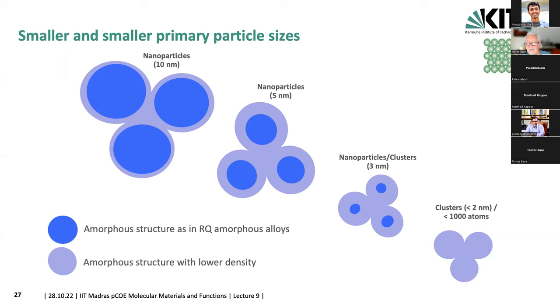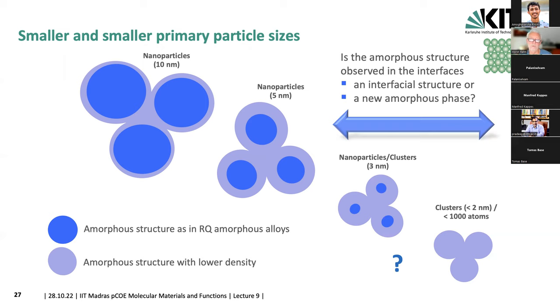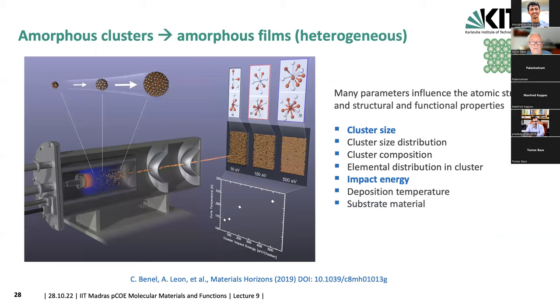So that's why we tried, instead of doing a mechanical compaction, we did the impact of the clusters on the substrate. And this is shown here very schematically out of this paper, which was published in Materials Horizons. You see in this schematic here the cluster source, and we extract the cluster beam. And now we can build a film of clusters only, where the clusters are always identical, but the deposition energy can be soft landing or hard landing.